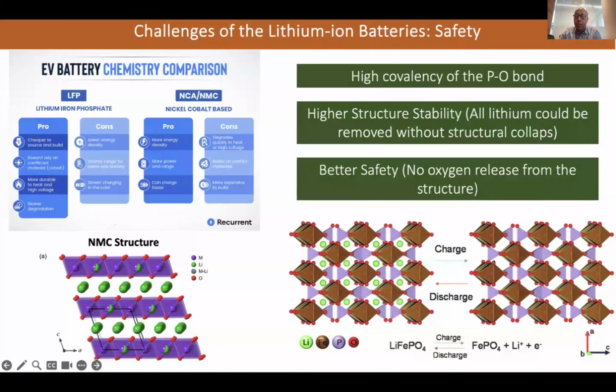And you see here, this is LFP, for instance. During charge, we can remove all the lithium. If you have a huge quantity of lithium, this means high capacity. And during discharge, we can get all the lithium back. So we get the full existing capacity in LFP. In the case of NMC, the structure is layered like this, and lithium here is stabilizing the NMC structure. If you remove all the lithium, the structure collapses and your battery will die. That's why we are using only about 60 or 70% of the lithium of the existing capacity. This is one of the reasons to encourage people to work on LFP-based material.